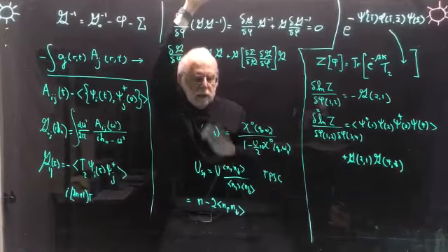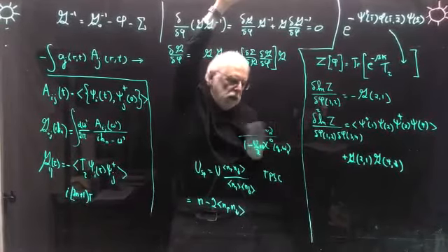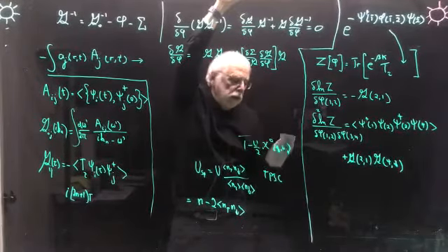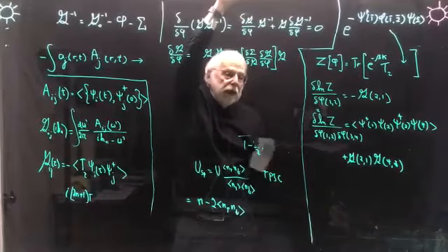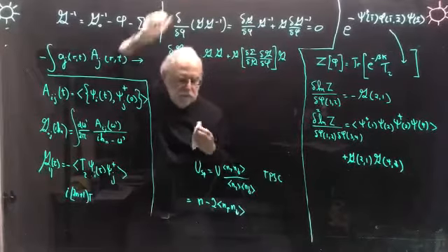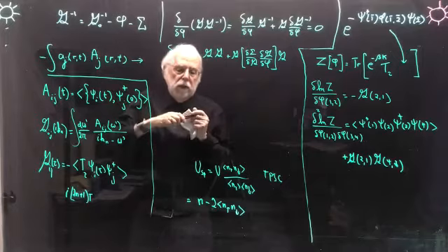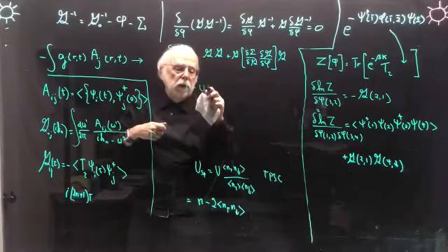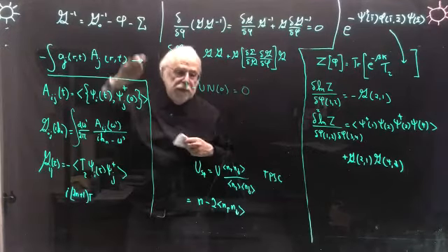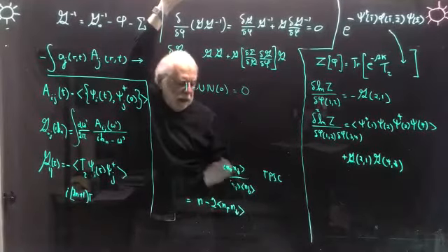broken symmetry. That's the last topic. So if we just look at what I'm erasing now, in the case of Q equals 0 in 3 dimensions, we find that in the normal state, this uniform spin susceptibility diverges at some temperature or some value of U, depending. I mean, at 0 temperature, the criterion is U minus single particle density of states is equal to 0. So we fix that by breaking the symmetry. And so in other words, we give a net magnetization.